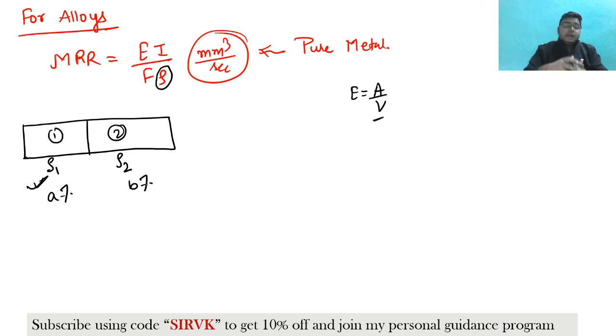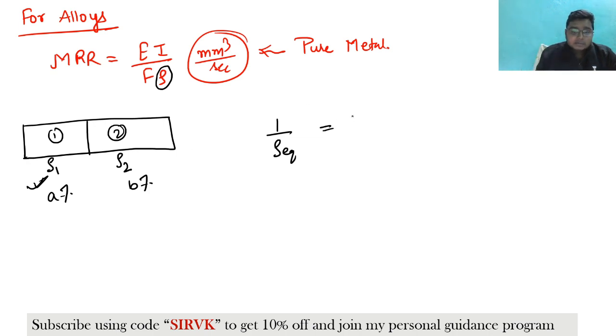So we have to find the MRR in a very different way. Now try to understand here. I'm just writing here. So basically 1 by rho equivalent. If you want to find the equivalent density, that is given by summation of xi by rho i. Let it be 100 so that you can put it directly in the percentage form.